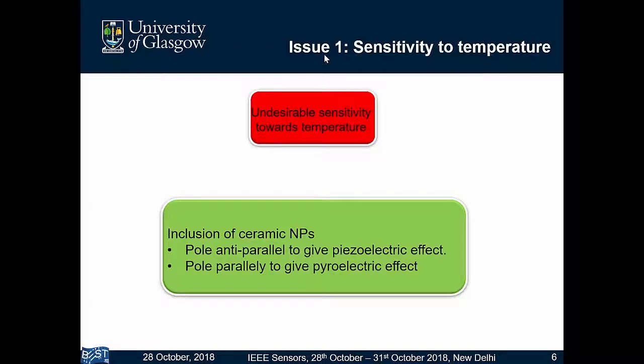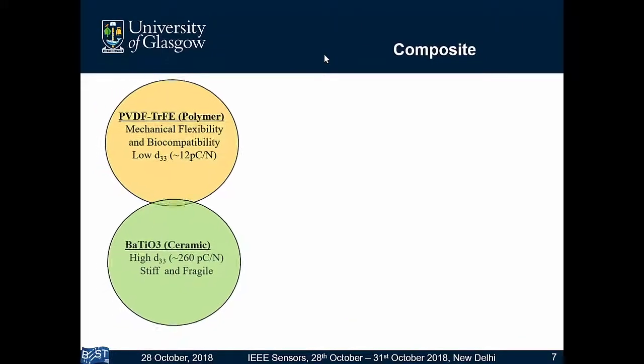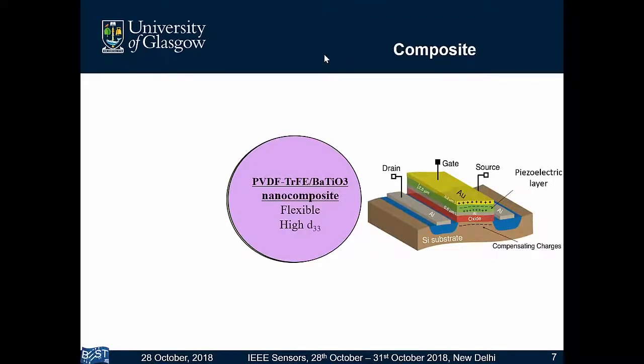Barium titanate is also a piezoelectric ceramic. Both have opposite piezoelectric property, but similar pyroelectric property. So we make a nanocomposite, which combines the good properties of both of them. The nanocomposite was flexible like PVDF-TrFE, and it has a higher piezoelectric property coming from the barium titanate. And then we combine it with a MOSFET.